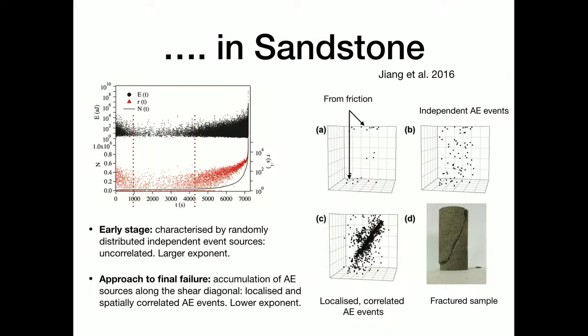Very close to the final failure, which you can see is along this plane, there is a huge localization of the next level of activities, and this whole growth of damage has been split into early stage and approach to final failure. And as you can see very clearly, there are randomly distributed independent event sources, and these are associated with a larger exponent, and these correlated events are the ones which have the lower exponent.